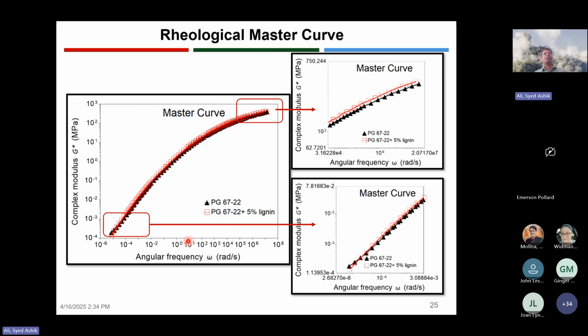Okay, so as we have seen, the 5% lignin is not showing much difference both on the high end and also on the low end. So we wanted to develop this rheological master curve, do the testing at different frequencies, and try to understand, is there actually a difference between the neat binder and the 5% lignin modified binder at a broader spectrum, at different frequency, and obviously frequency can be converted to temperature as well